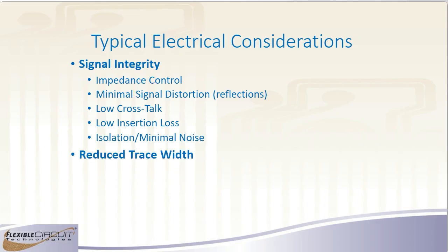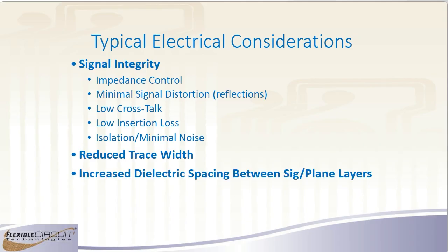Typically, when you do have signal integrity issues, it goes with impedance control, and that's usually a reduced trace width. You have to increase your dielectric spacing between your signal and plane layers. I don't have a specific slide stating this, but one thing about impedance control is you will always have at least one plane layer and typically 2 plane layers, and those will have a huge impact because you're adding 2 additional layers that wouldn't be there if you did not have impedance control. So it's important to keep in mind that that's going to have a big impact, especially if you're using copper for those planes. And I'm going to address that a little bit further in here.